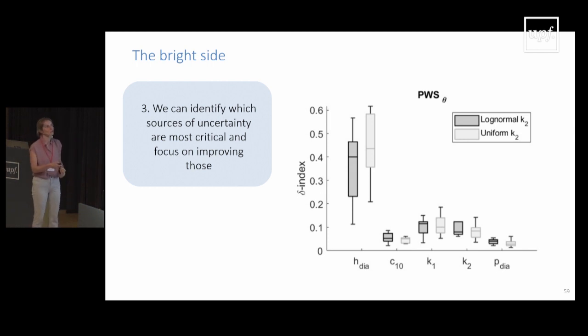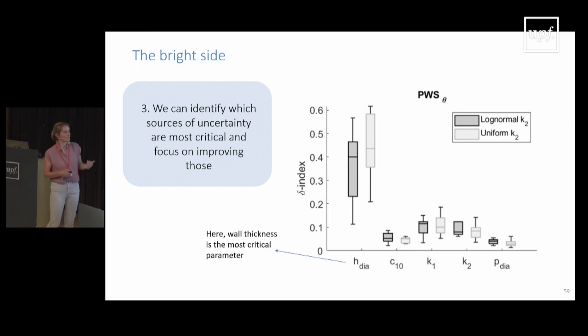In our case we looked at the delta moment-independent indices. This means that the higher this value, the larger the effect it has on your output value of interest, which in our case was the peak wall stress in the circumferential direction. Not very surprisingly, the wall thickness is the most critical parameter for us to really make sure that we get as correct as possible. So it gives you an idea of how to deal with that whole swamp of uncertainties, and try to pick out at least those that are the most important, and tell your experimentalist colleague to focus on that one.